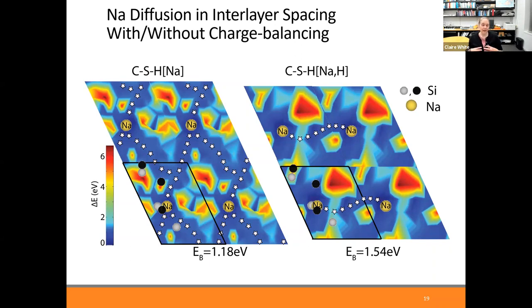Is the atom able to easily diffuse around, which would be an indication that that element can easily leach out of the system, for example, or is it kind of stuck quite well in its location and it can only diffuse in the local vicinity of where it originally sits? Here, what I'm showing is just for sodium in the interlayer with and without a hydrogen charge balancing mechanism. Without, we find the barrier to diffusion is 1.18 electron volts. You can see the barrier increases when you charge balance using a hydrogen atom.